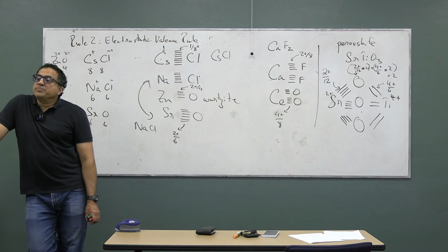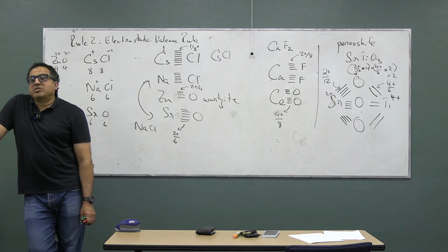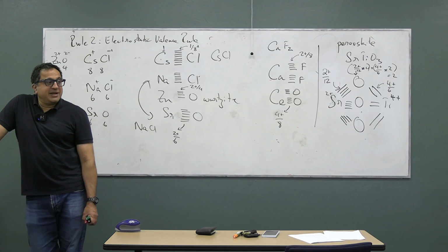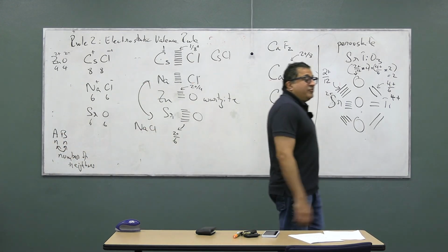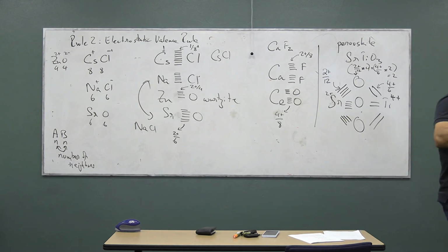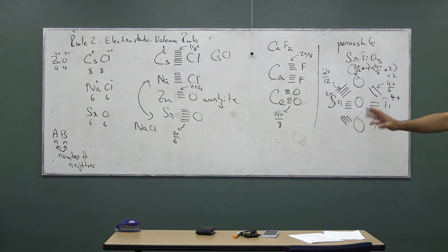The reason you do is because it's not a salt. In fact, it's metallic. It's a pretty good metal. Titanium nitride is extremely electrically conducting because it's got a free electron floating around. Titanium behaves like it's 3 plus with an electron, and that electron floats around the structure. Right? So when these rules fail, it means you don't have a salt. Something else is happening.